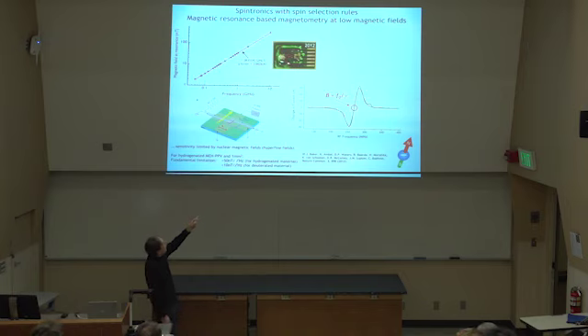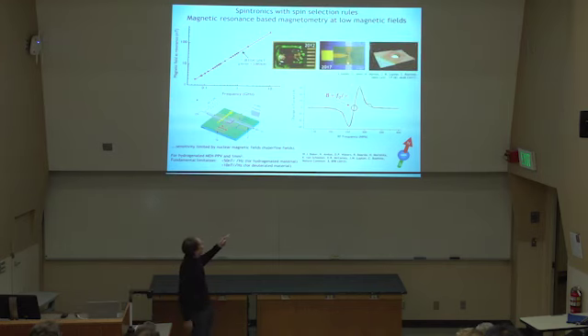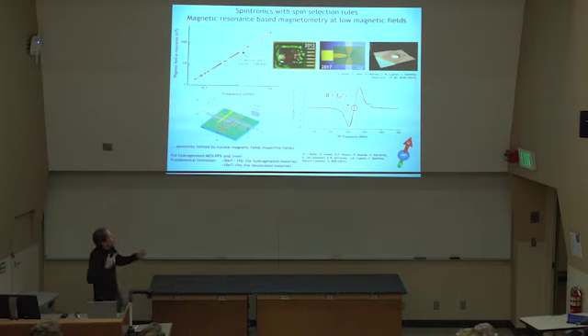And these copper lines, that's where our magnetic field was produced. Five years later, or actually four years later, now five years, last year, it looked like this. So we'd scaled it to about 50 microns. And we've really built it not just like two substrates that are flipped together, but really pixel-sized magnetometers, which have a demonstrated sensitivity of about 600 nanotesla per square root of hertz. So you can make the absolute sensitivity. And of course, we are continuing to pursue this just technologically.